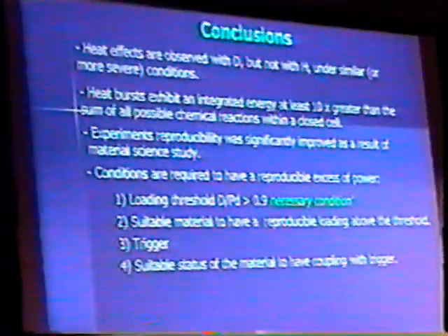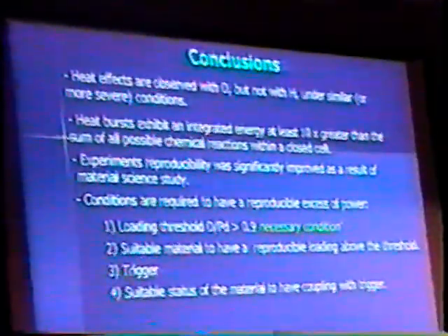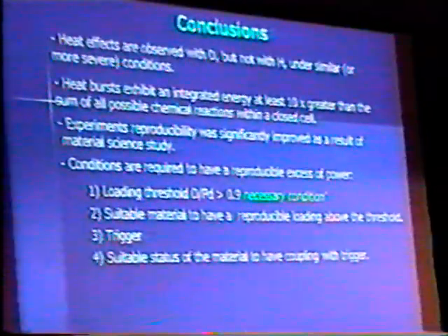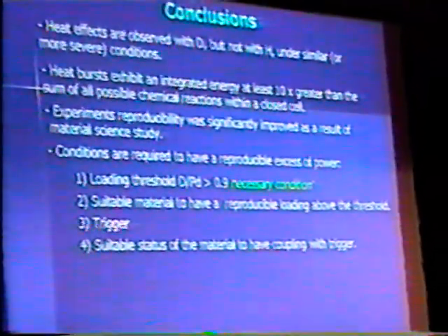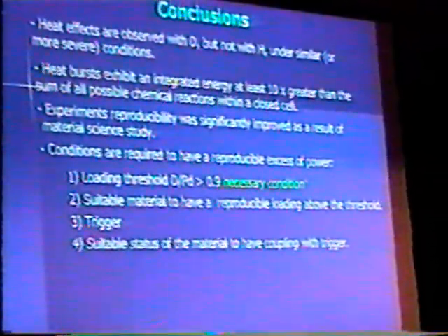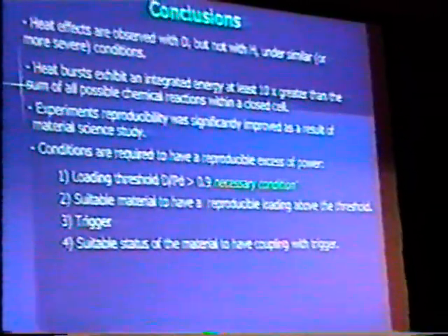Conditions are required to have reproducible excess power. A loading threshold of D per PD greater than 0.9 is necessary. Suitable material is required to have reproducible heating above the threshold. Triggering through things like lasers is helpful. Suitable status of the material to have coupling with trigger. So you have to get this right, and you have to systematically do it.